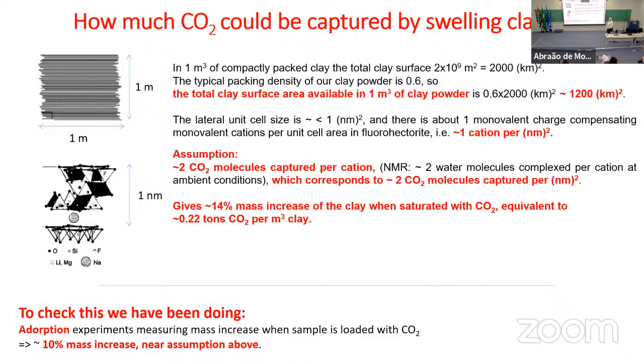Now we know that there is about one cation sitting in these interlayers per square nanometer. If we assume that each of these cations can capture two CO2 molecules, like it can capture easily more than two water molecules, this should give a 14% mass increase of the clay when it's saturated with CO2, which is equivalent to 0.222 tons CO2 per cubic meter of clay, if you do this exercise. We actually checked this by weighing the clay, exposing it to CO2, and looking at the weight increase, and it matches more or less. We got 10% mass increase instead of 14% mass increase in the clay that we studied.